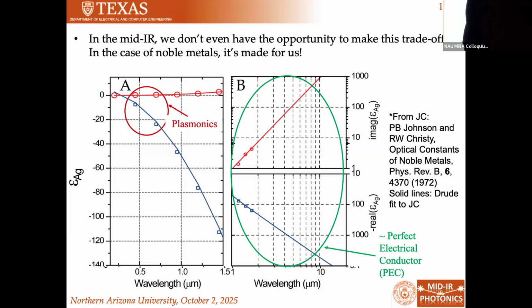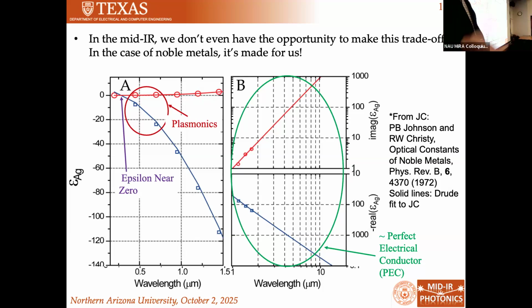Where you have permittivities that are on the order of the dielectric that you could expect from an electronic material. And then there's this kind of neat physics range where your permittivity actually crosses to 0. There's some interesting stuff there. So what this means is that even if we wanted to leverage these trade-offs with traditional metals in the mid-infrared, we couldn't do that.